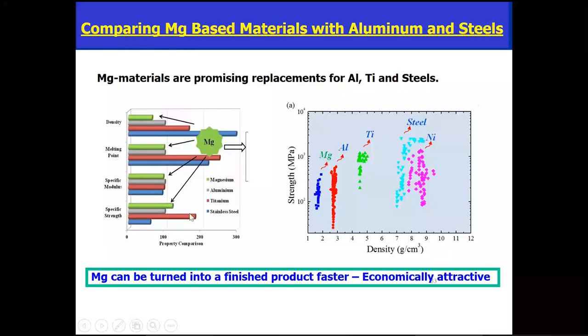Now, if you look at the graph on your right-hand side, you see on the y-axis you have strength and on the x-axis you have density. Now you see these blue dots here. In these blue dots, there's a large range of strength where it overlaps with aluminum, titanium, steel, and nickel. So wherever the weight is an issue, you can replace all these heavy elements by magnesium. Moreover, it can be turned into a finished product very fast, so it's economically attractive because your productivity or manufacturability is high for this element.